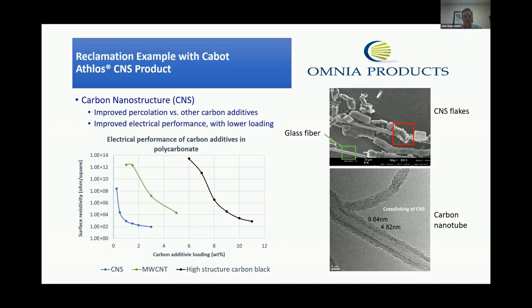The advantage is it has a high level of percolation compared to other carbon additives. So it provides a continuous structure with less material. And this allows, as indicated in the chart below, an improved electrical performance with lower loading. So you can see the CNS in the blue on the left, less than 1% has an equivalent ESD rating to that of other additives, such as a carbon black material. So very, very interesting material.